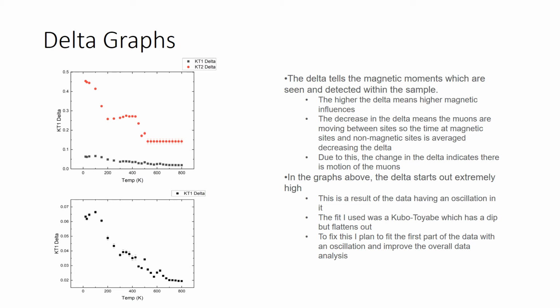A change in the delta, or a decrease in the delta, means the muons are moving between sites. So the time at magnetic sites and non-magnetic sites is averaged, which decreases the delta. Due to this, the change in the delta indicates there is motion of the muons going between the different sites. In the graphs above, my delta from my fit starts out extremely high.